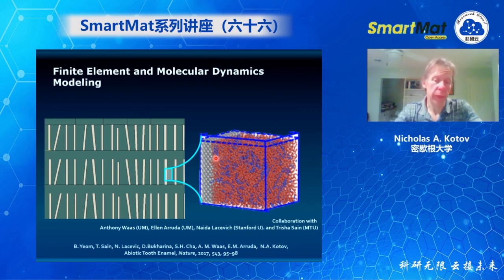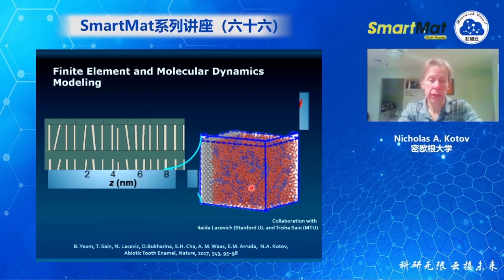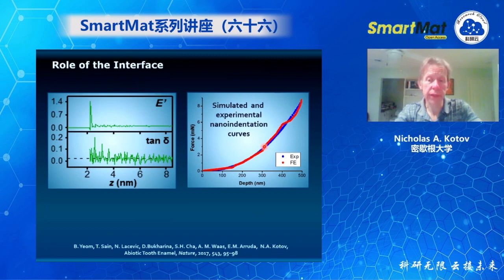By using molecular dynamics in collaboration with Anthony Waas, Ellen Arruda, Naida Lacevich, and Trisha Sain, we modeled the stress propagation through the stiff zinc oxide rods. And it turns out that there is a very efficient translation of stress if the interface is organized in that way. And if we model, say, the mechanical properties here, then we have a virtually complete match with experimental data.